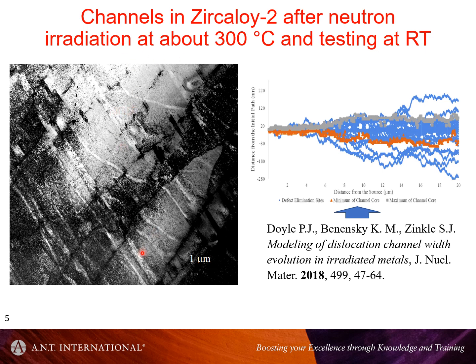So channeling is this phenomenon where the gliding dislocations sweep through the material and pick up the prismatic dislocation loops. What that means is that you might start off with a slip band or a slip plane where all the dislocations are in one plane, but as they sweep up and accommodate the loops, their slip plane will vary, and the channel height, if you like, will broaden. If you imagine this, we're looking parallel with the slip plane, in the direction of the shear, a distance along from the source where a dislocation slip band,